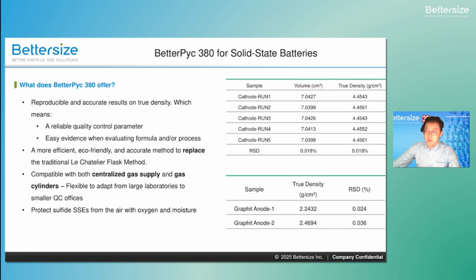the BetterPyc 380 turns true density into a rigorous quality control parameter. If you look at the data on the right, 5 consecutive runs on the cathode material yielded a relative standard deviation (RSD) of just 0.018%. This level of precision is impossible with the traditional messy Le Chatelier flask method.